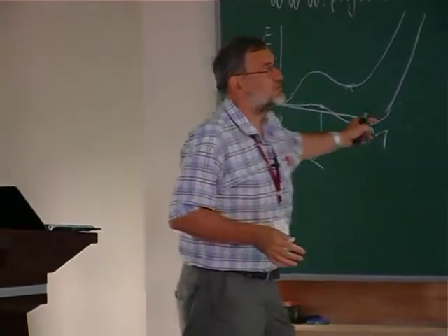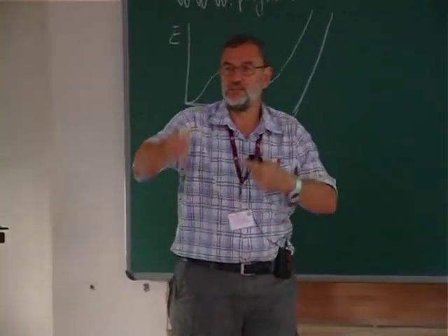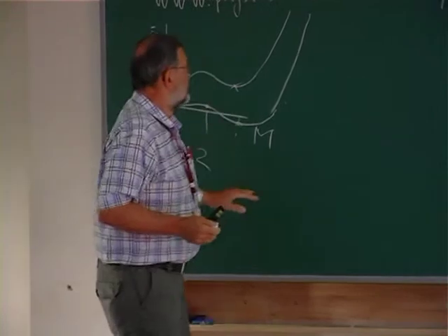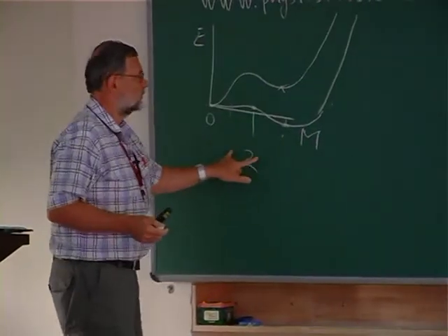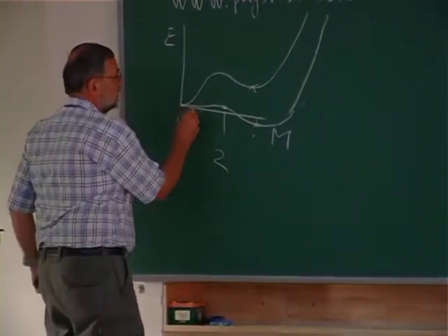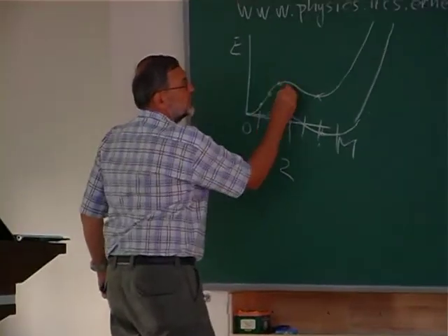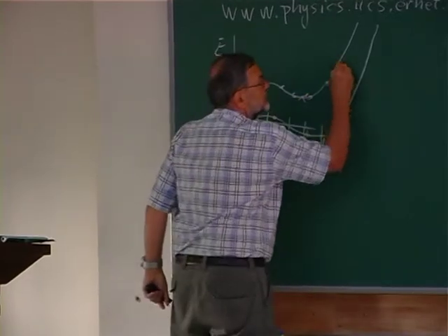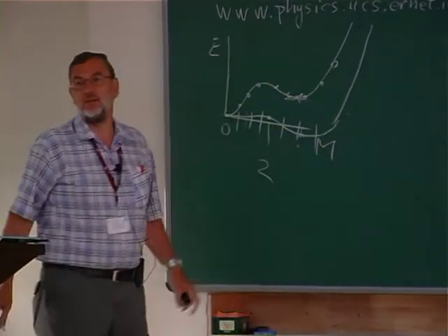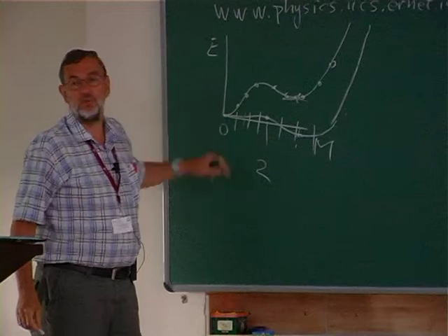Okay? But with this trick, I can do, so to say, the reverse engineering. I can look what would be the field for a certain magnetic moment. And I can do this calculation now for a couple of points and map out this energy curve and find that there is this meta-magnetic transition probably.